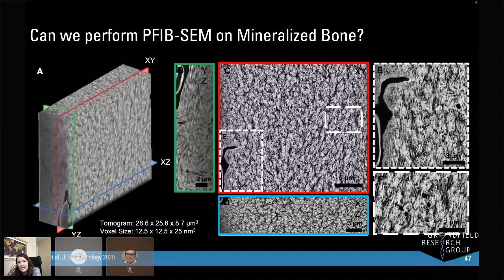The second really exciting thing about using plasma FIB was we were able to do this also on tissue where we didn't remove the mineral. In the previous slide, you'll have seen very little contrast, but in this slide, you'll see really bright differences of white zones and dark black regions. In this case, we left the mineral intact, so this is the bright zones, and anything you see in black is representing cell networks or open space, porosity.